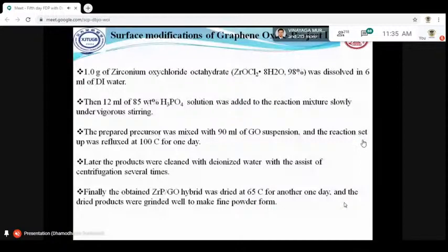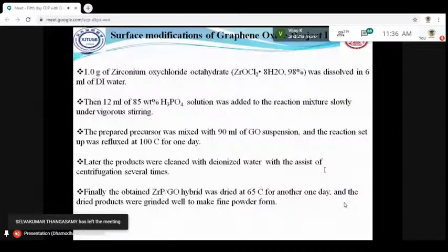and also zirconium phosphate has a smectic nature. Smectic nature means that while curing, the arrangement of the nanofillers becomes horizontal in layers, and this horizontal layer will make a better shielding effect. So we planned that it will surely inhibit the electrolyte from entering the surface of the polymer. That's why we planned to work with zirconium phosphate.